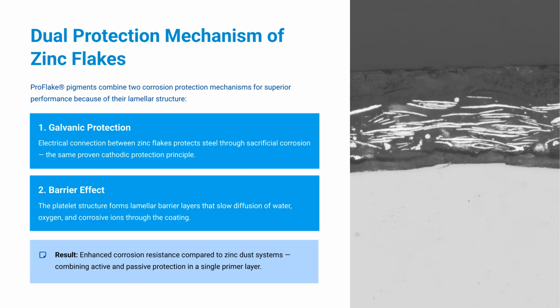Second, the platelet structure creates a lamellar barrier effect. The aligned flakes form overlapping layers that slow the diffusion of water, oxygen, and corrosive ions through the coating. This combination of active and passive protection results in enhanced corrosion resistance compared to conventional zinc dust systems.